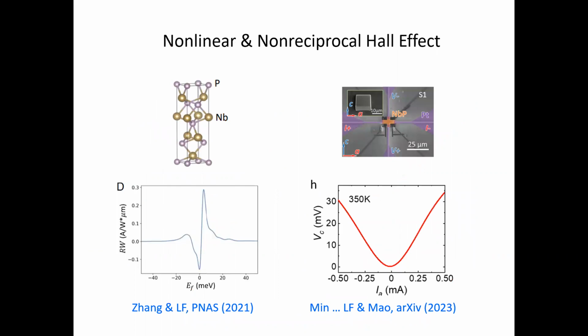So, since this 2018 experiment, there are many studies of this nonlinear Hall effect, both computational, theoretical, and experimental. And with my former postdoc, Yang Zhang, we used again the computational methods to study the electronic structure and Berry curvature dipole of various materials. And we found that some metals, in particular this niobium phosphide, should have a large nonlinear Hall effect. And this is a tetragonal crystal, again, with a polar axis that breaks inversion symmetry.